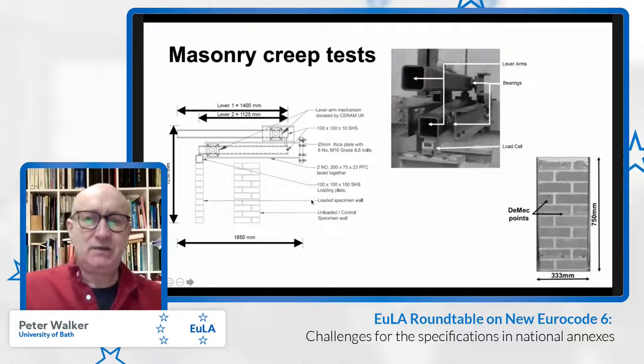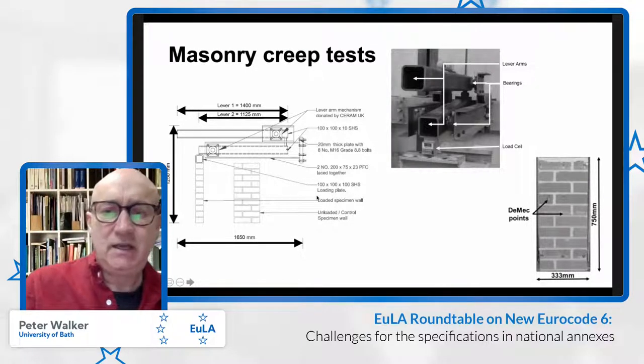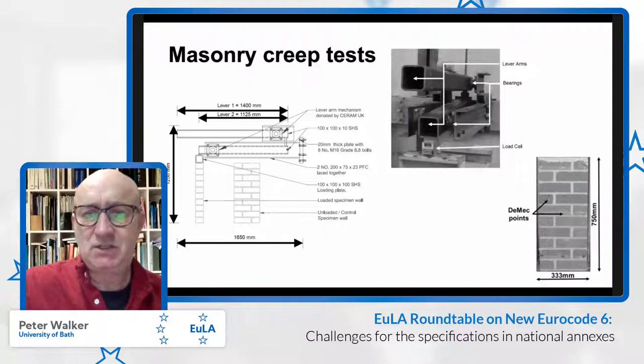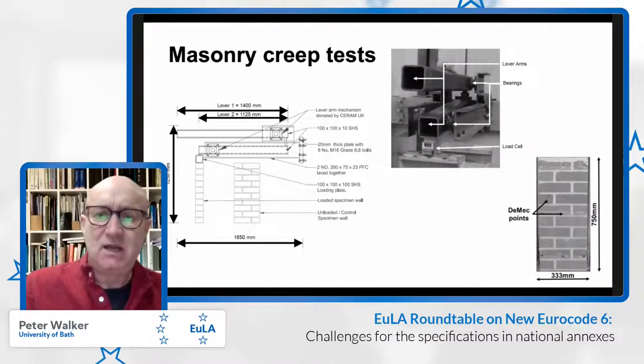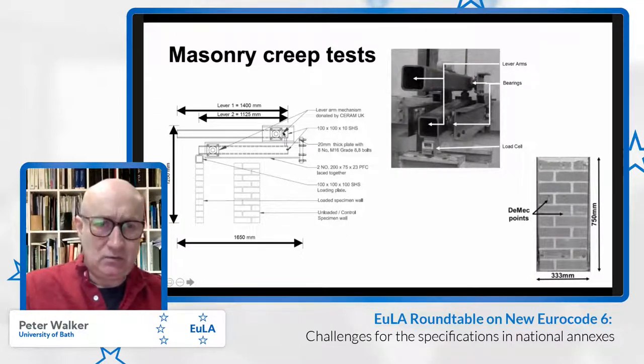For the creep test, we housed the units within our structures lab, but encapsulated and built an insulated cabin in which we were able to control the temperature and humidity during the tests, which each time ran in a series up to 6 months. We were able to use a lever arm arrangement, which had a very efficient lever arm, to allow us to get a stress of 2 newtons per square millimeter into these walls.